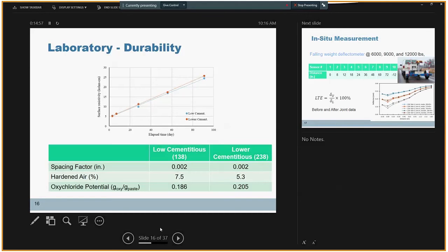And the problem here was the potential for oxychloride formation. So we used the differential scanning calorimetry test method to determine the potential for oxychloride formation for the binder used in these two concrete mixtures. With 25% fly ash, we had 0.18 and 0.20 gram of oxychloride per gram of paste potential for oxychloride formation, which is higher than the recommended limit of 0.15.